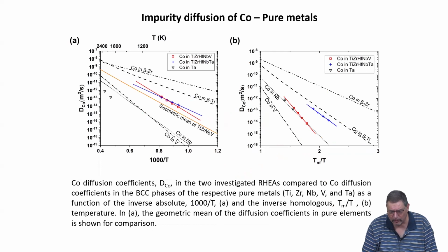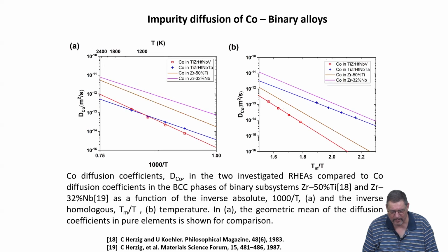When we do this again for the two temperature scales, homologous and absolute, look at the impurity diffusion coefficient of cobalt in these two refractory high entropy alloys and compare it again to cobalt diffusion coefficients in other BCC matrices, and compare it also again to the geometric mean of the diffusion coefficients, then again it looks like we have enhanced diffusion on one temperature scale, retarded diffusion on the other one, but it's not a big effect.